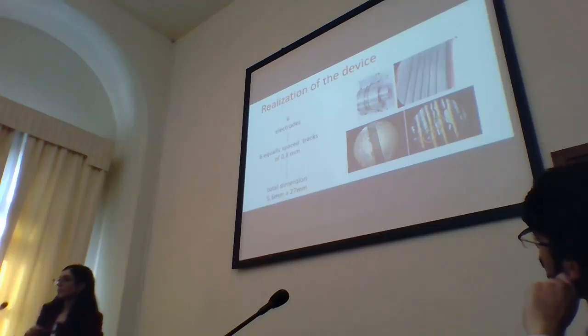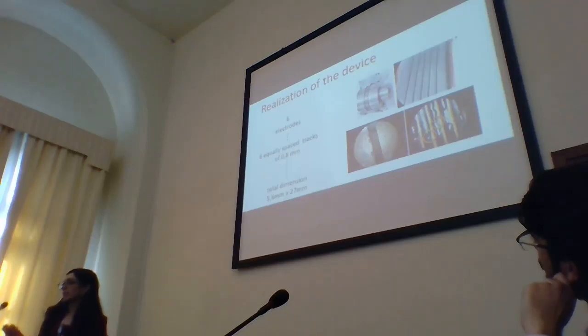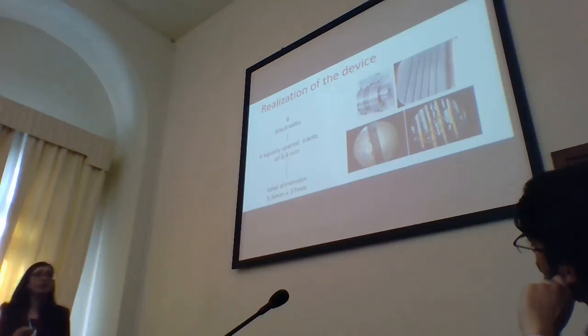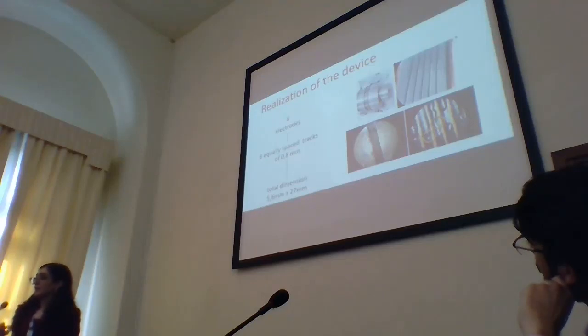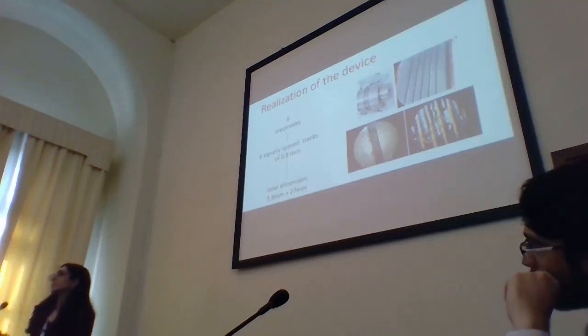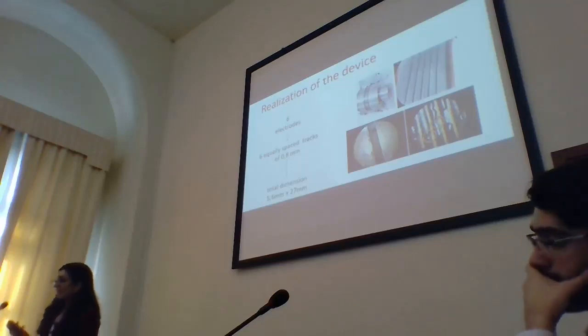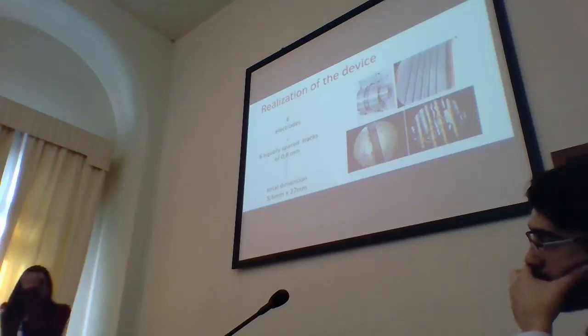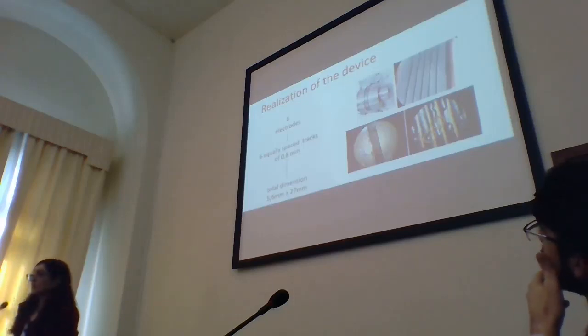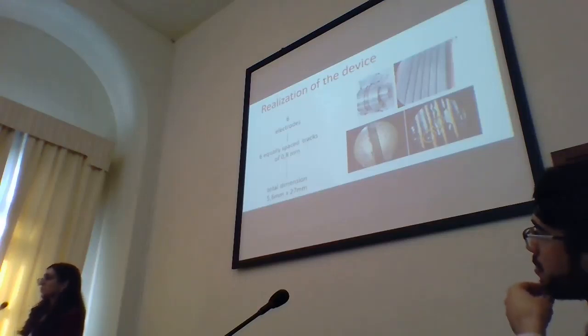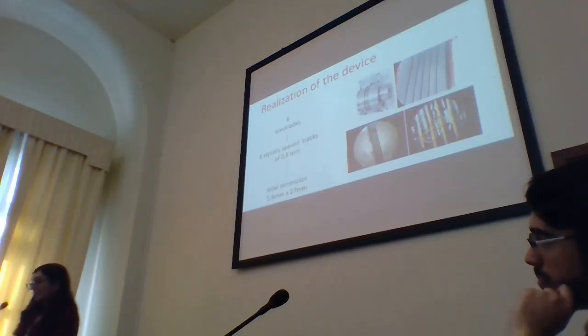so we can make the temperature of the polyethylene increase, and at around 180 degrees, we deposit by drop casting our suspension of single-wall carbon nanotubes with ethanol, water, and SDBS. After the deposition, the film reaches a temperature near its melting point. And after we repeat this procedure 3 times in order to obtain uniform and compact tracks, we can analyze our device.